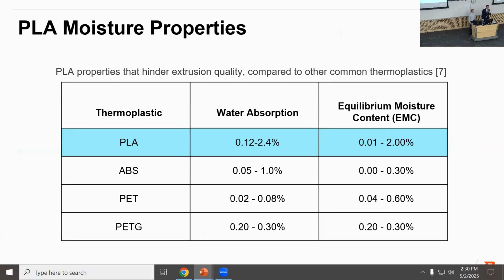Unfortunately, it does also have some negative aspects, specifically with the water content. It has the ability to uptake up to 2.4% water, and it also has a resting equilibrium moisture content of up to 2%. Both of these values are double the next closest one, so PLA does struggle in this regard.